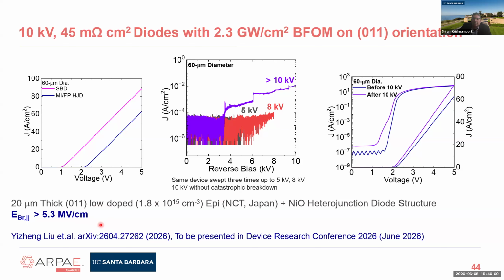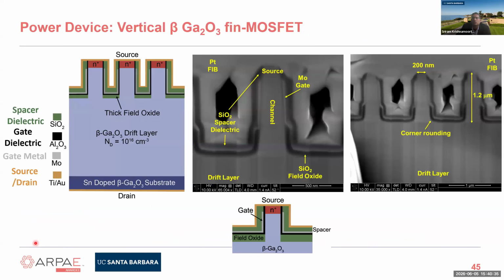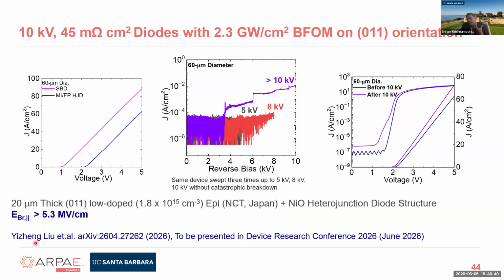So this is very recent results to be presented at the Device Research Conference in Michigan later this month by Yizheng Liu. So we are starting to see these 10 kV diodes, and there are also reports from University of Florida. So they've been able to measure up to 13.5 kV in gallium oxide as well. And there are lots of papers from China where they're starting to report high breakdown voltages as well. So it's quite an exciting time for the material. So that's the diode. So constant progress in terms of high voltage, low stored charge diodes.